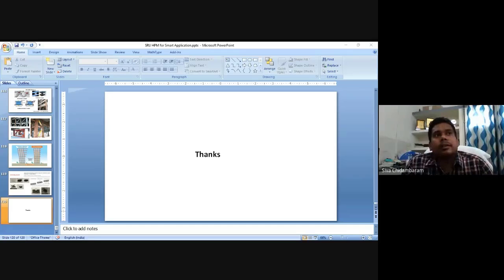So bamboo, you can replace the reinforcement just for earthquake bands. If you are talking about earthquake bands, you can replace the normal reinforcement, and that will give you wonderful integrity. But if you think my entire building can use it, no. We have tested a few beam-column joints with bamboo, and it can give a good amount of energy dissipation. But when it reacts with cement, obviously it will degrade. So it is only applicable for non-structural elements. Complete replacement of reinforcement in our conventional RCC frame by bamboo is not possible.